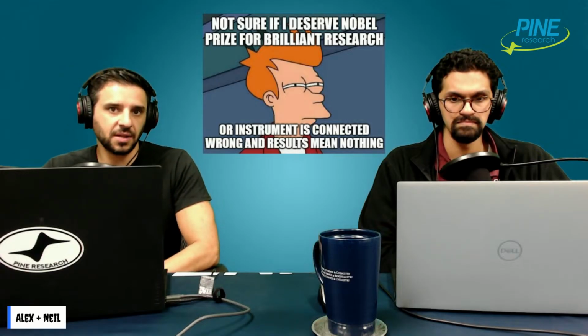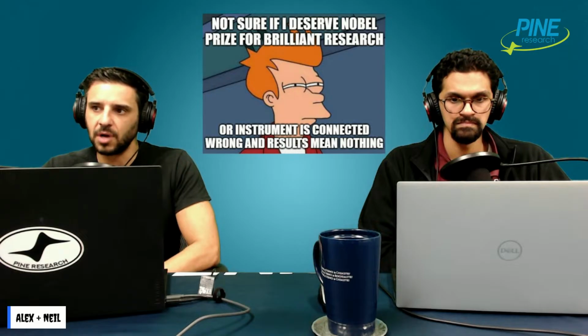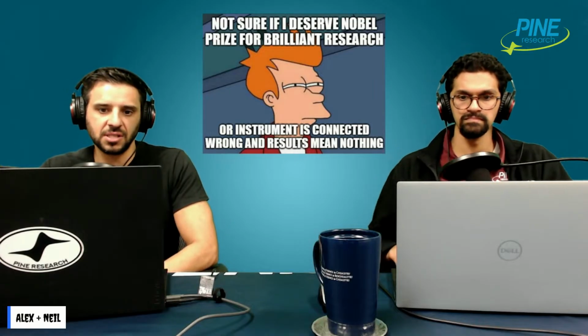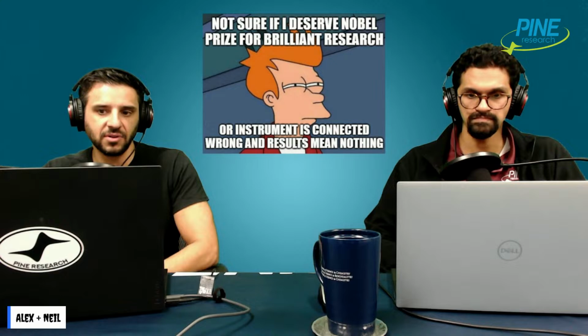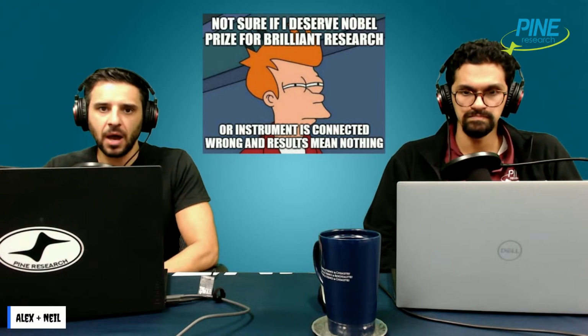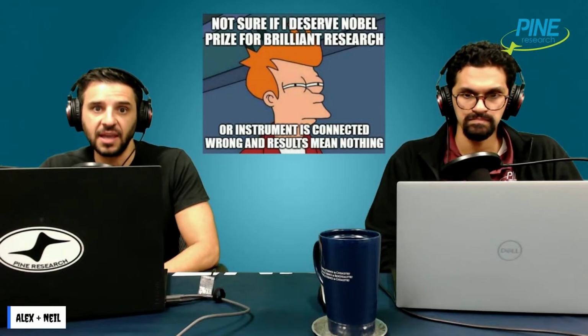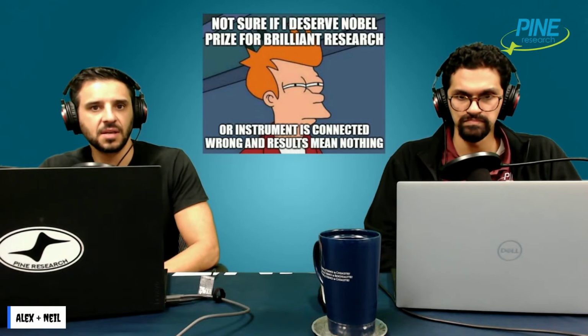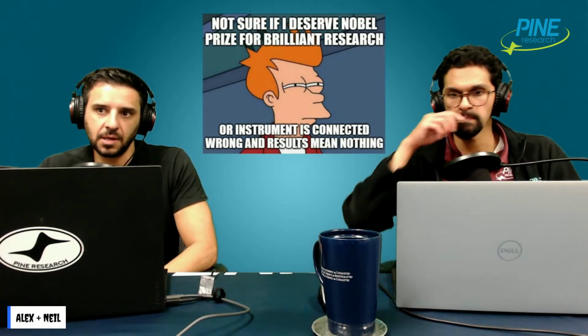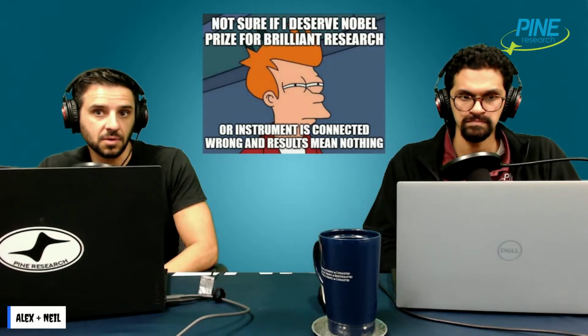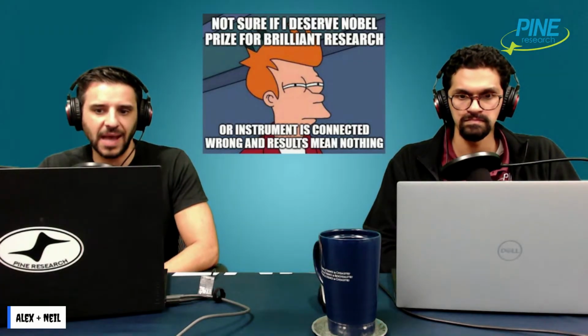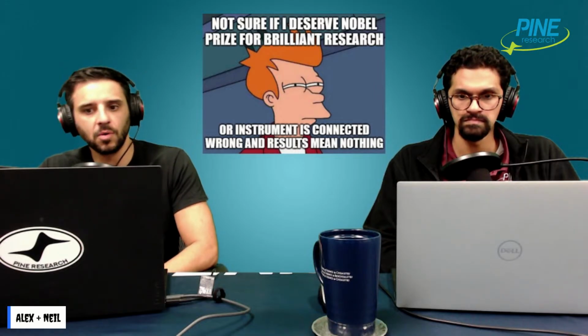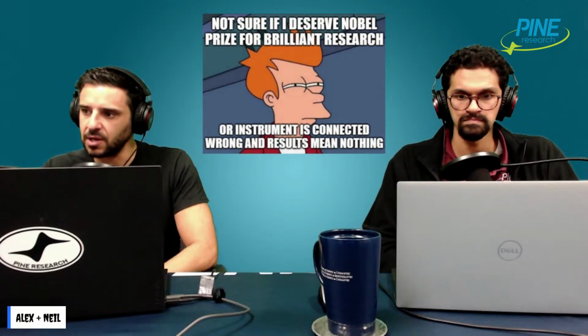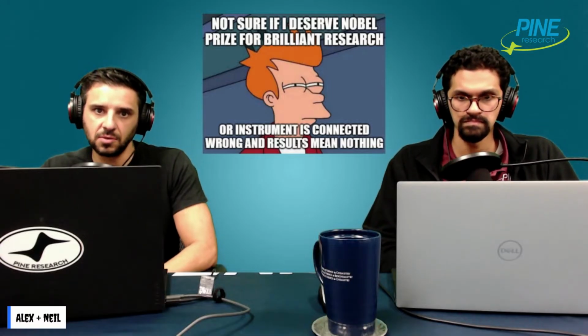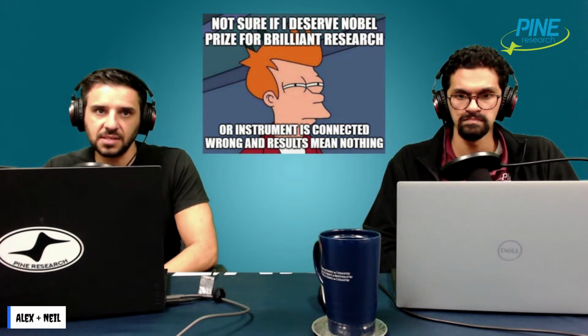So there are ways of getting around this. People do rotating electrodes, rotating disc electrode, RDE and RRDE experiments, as a way to deconvolute mass transport from kinetic current. Levich and Koutecky-Levich analysis allows you to do that. That's one way. Beyond that, there are very, very painfully slow scan rates. That does theoretically allow you to minimize capacitive effects. It doesn't necessarily eliminate mass transport effects, but at least the capacitance will be relatively minimized, so some of this non-Faradaic surface charging can be minimized, allowing you to assume in some cases that it's mostly kinetic current.